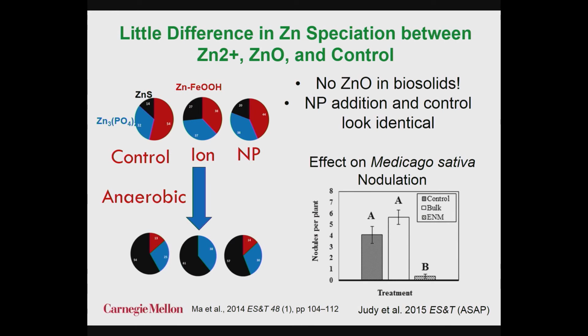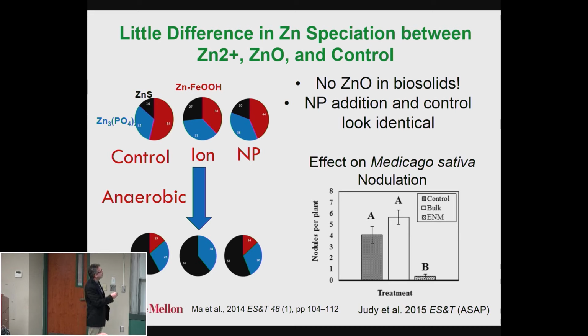Well, we put zinc oxide in and we measured the speciation of zinc leaving the system. And it turns out if you look at zinc speciation, you get zinc sulfide, you get zinc phosphates, and you get zinc on ferrihydrite. What you don't get is any zinc oxide nanoparticles whatsoever. They dissolved and they sulfidized, or they adsorbed onto ferrihydrites. So if you're doing experiments with zinc oxide in biosolids on fields, that's sort of a silly experiment because there is no zinc oxide.